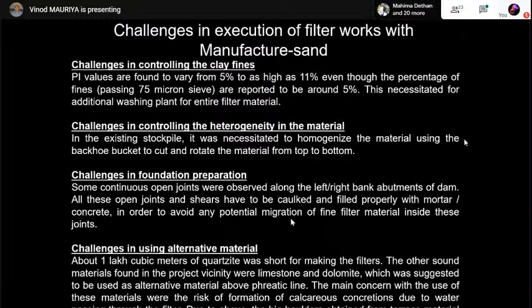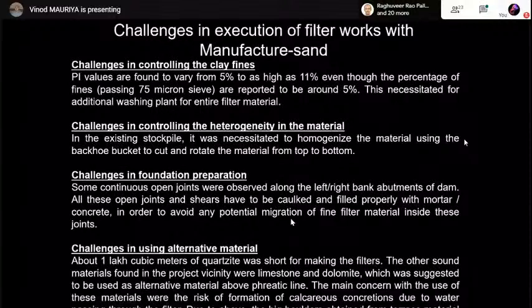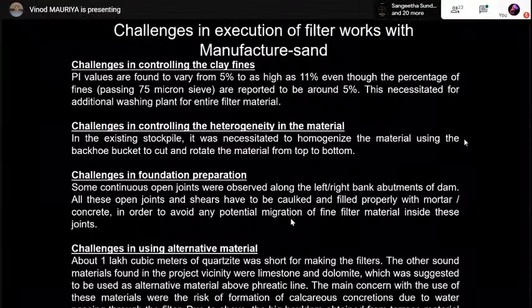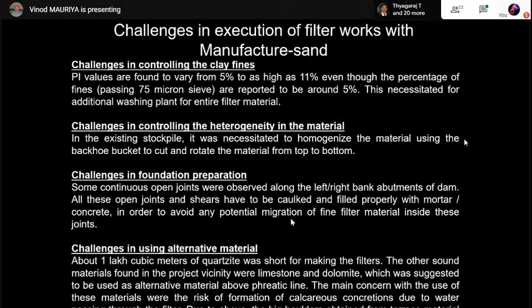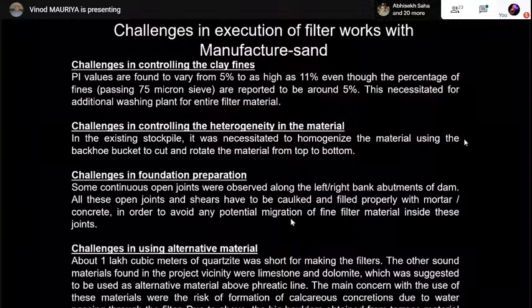The next challenge was that during actual execution, some of the quantities were short due to all these challenges. So we tried to find another alternate material which was locally available, limestone and dolomite, but that was having a problem of calcareous concretions. So that was avoided. So we found that there are a lot of big size boulders available which could be crushed and used in the filter material. That was also explored because of the shortage of quantity, and it was very successful because the boulders had a lot of quartzite. So through that, we could overcome the challenge of the quantity shortage also.